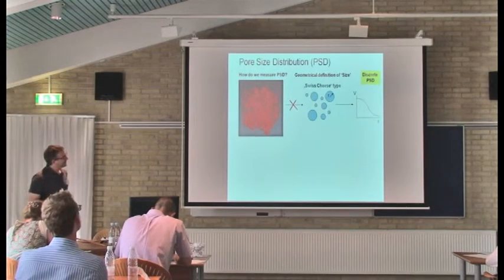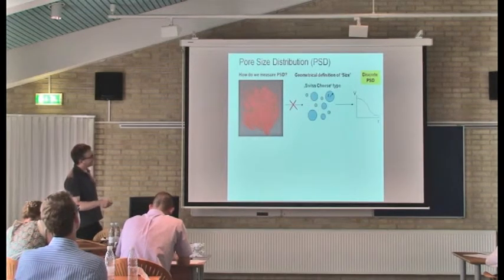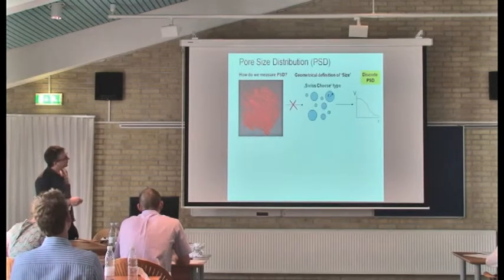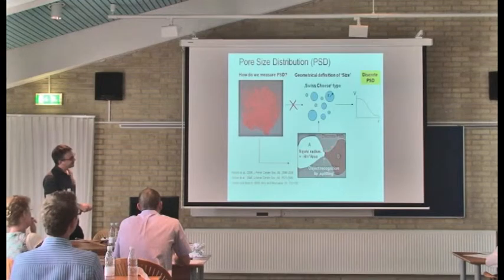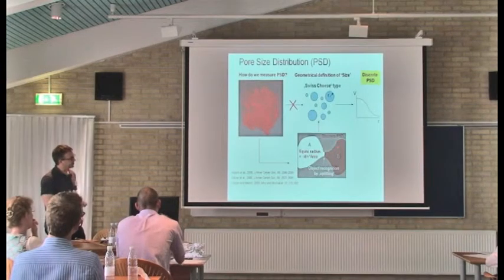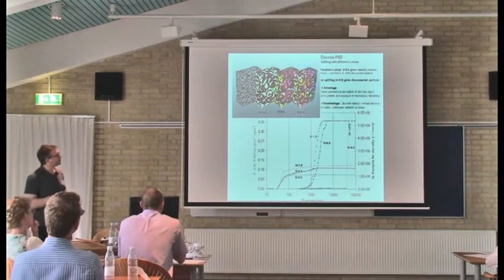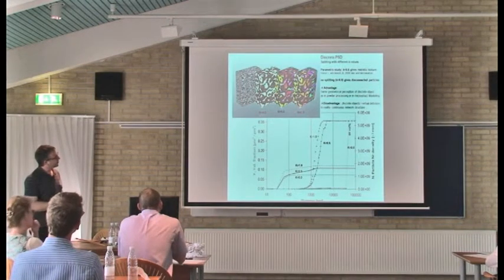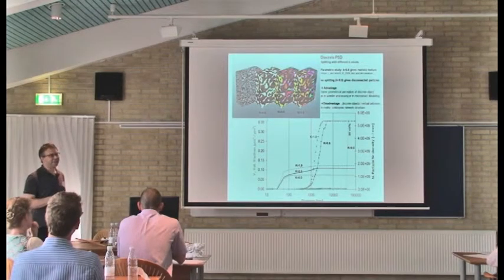There's an algorithm that does splitting at the necks. When we do the splitting correctly, this will give us discrete objects. I would call this approach the Swiss cheese type view of what the pore or particle is. But very often we do have complex continuous features. This splitting is actually not that easy, and it's also not a one-zero solution. It depends on the curvature and so on, and there's actually no real physical or theoretical solution for that.